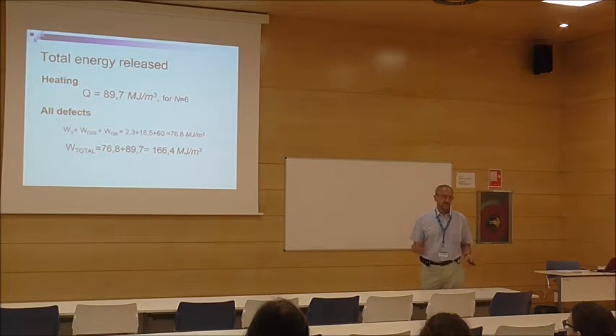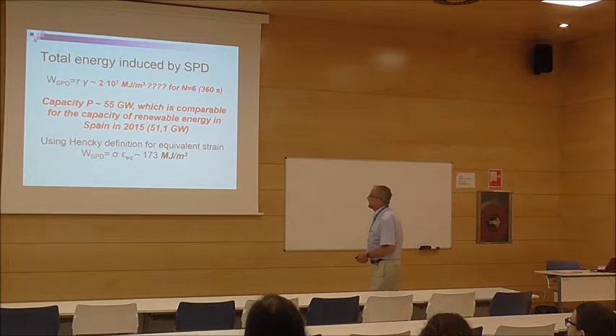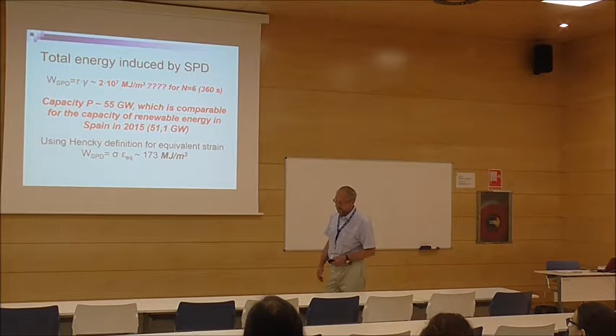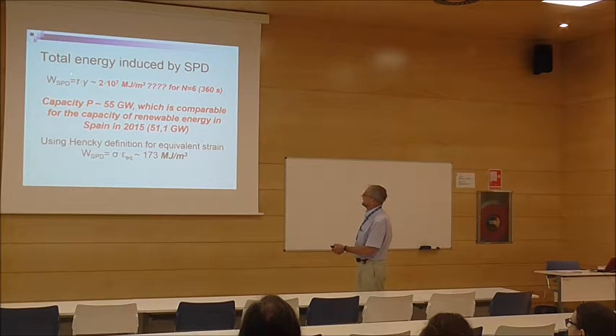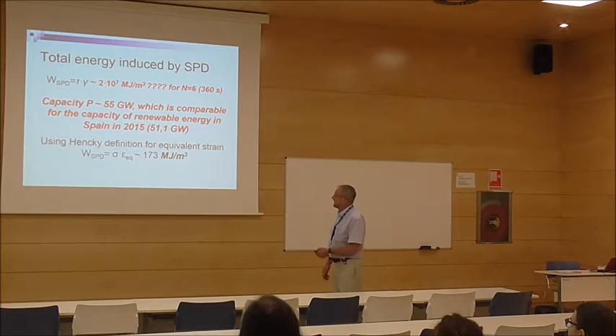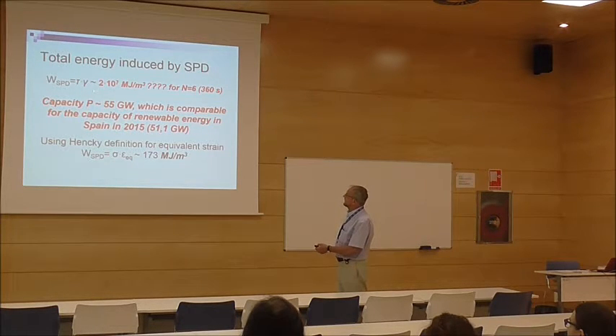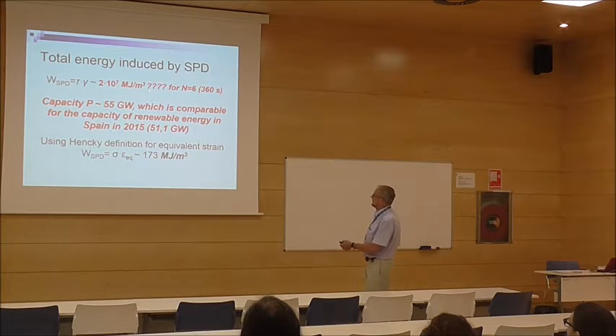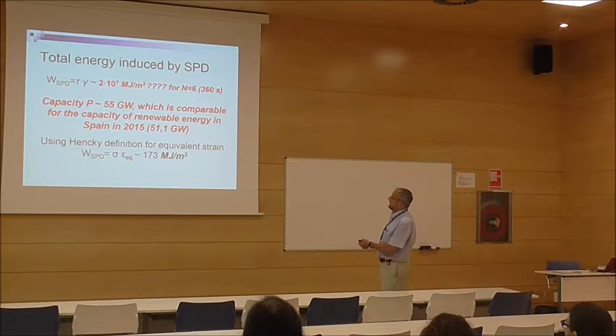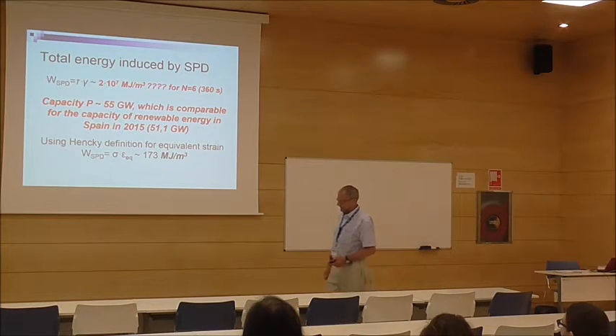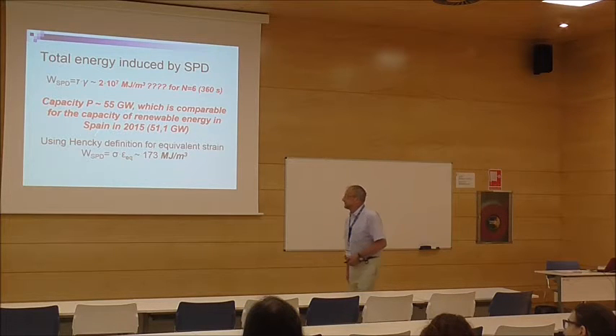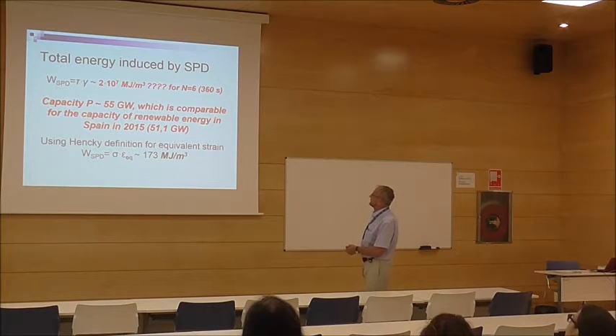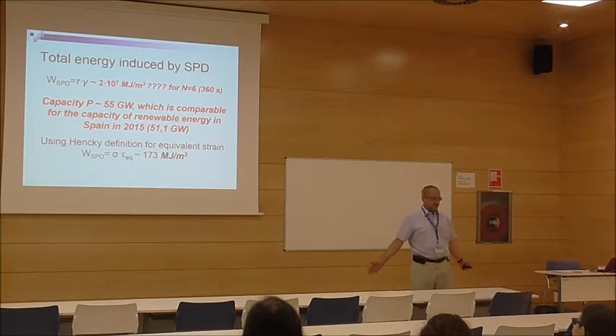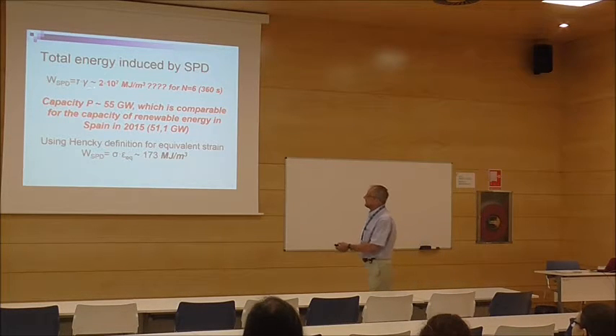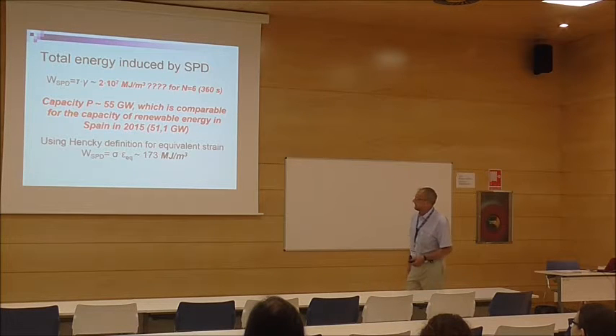Okay, is this good or bad? I don't know. But if we calculate the plastic strain energy by shear strains, and we take two samples like this, it gives like 2 times 10 to the 7 megajoules per cubic meter for n equals 6. If we divide it by time, which is 360 seconds, we will get a capacity of 55 gigawatts, which is comparable with the capacity of renewable energy in Spain in 2015. So it's impossible. That means this calculation using the von Mises strain is incorrect.